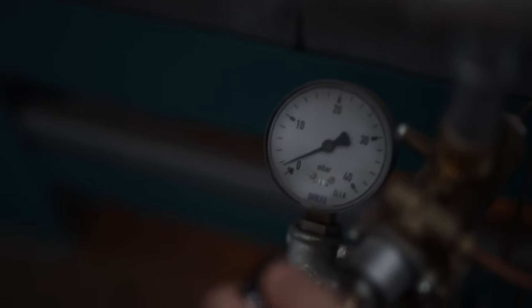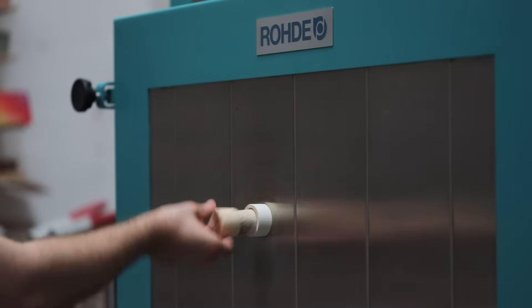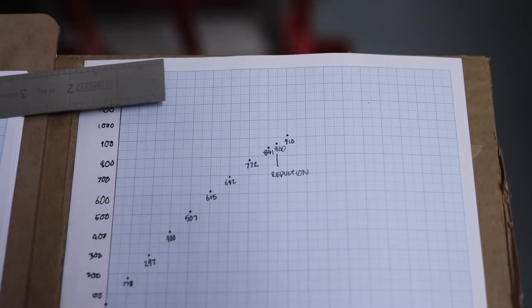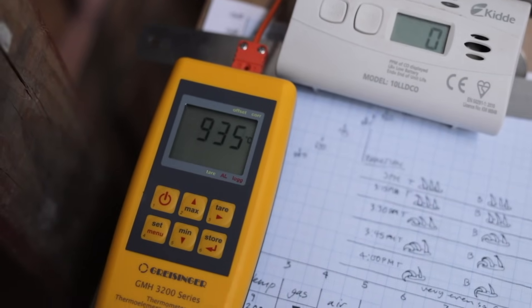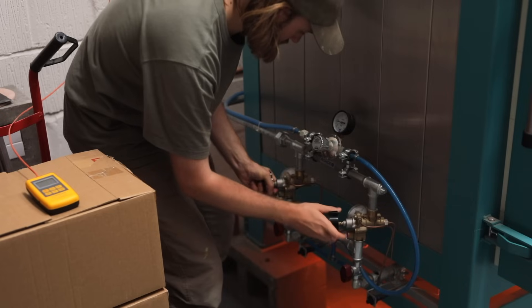There are four burners for this kiln, and alongside the gas, there's also some forced air provided by an air compressor. The two are gradually increased together, and the entire process is manual, but that doesn't mean I have to spend the entire day watching the kiln. Instead, I check it every half hour and adjust it accordingly. At 860 degrees precisely, I initiate reduction. I do this by increasing the gas pressure to 10 millibar and the air pressure to 0.4 bar, as well as sliding over the dampers halfway across the exit flues on the back. This causes the internal atmosphere to burn with insufficient oxygen, and as a result, the burning gas inside — which is seeking oxygen — begins to strip away oxygen molecules from iron molecules inside the clay and the glazes, thus changing their colours to the characteristic blues and greens that my glazes have. If instead I fired these glazes in an oxidised atmosphere, they would appear yellow. As the temperature increases, I gradually open the dampers on the back by only tiny increments, and then finally, once it's the correct temperature, the gas can be turned off and the firing's over.